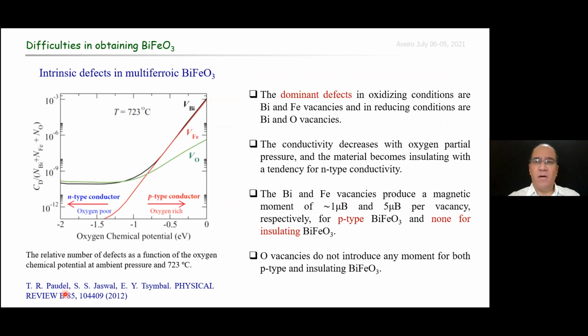In their seminal work, Paudel and co-authors summarized the intrinsic defects in BFO. They observed that bismuth, iron, and oxygen vacancies are present in the BFO system, but in oxidizing conditions, the bismuth and the iron vacancies are the dominant defects.